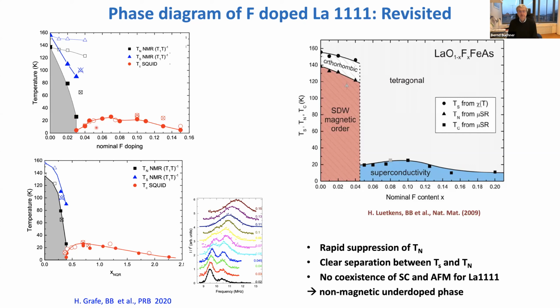So that's very similar to the first thing. We also managed to get, let's say, an internal standard. So the main problem is just to measure the electronic doping, and this you can do via NMR. And if you want to know more on that, you can have a look at this paper where we describe that. And you can even take all the literature data, put it on the same phase diagram, and then all the things fit together. So that's the phase diagram which we know for these compounds.